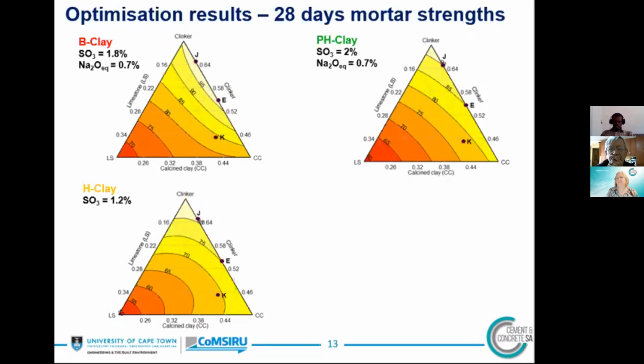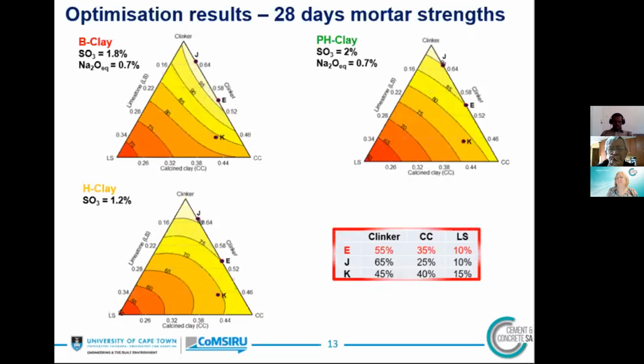Now, from the results, it's clear that for best performance, the lowest clinker factor is 0.55, which is point E, at which the calcined clay factor is 0.35 and limestone factor is 0.1. Now, because high strength does not necessarily mean high durable concrete, we decided to move up and down by 0.1 clinker factor for the concrete work. And the calcined clay and limestone factors, as you can see in this box.